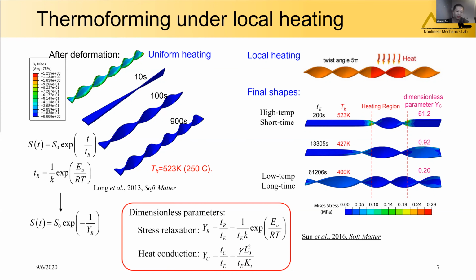For the uniform heating, the YR is sufficient to describe the relaxation and shape fixity effects. But for the local heating, the three cases shown here have the same YR but different YC. For the high temperature and short time case, the YC is high and implies a relatively slow heat conduction. So the relaxation effect is confined in the heating region. For the low temperature and long time, the YC is low and represents faster heat conduction. So the whole strip exhibits the relaxation effects.